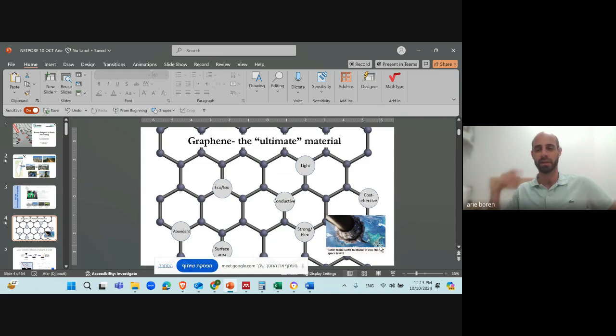Basically, you either use a very expensive method like CVD, and you have a very small amount of graphene, monolayered graphene, where all these physical and chemical properties are preserved, or you use other methods like wet chemistry, and usually you don't get graphene. You end up with very defected graphene or something that is more like graphite.